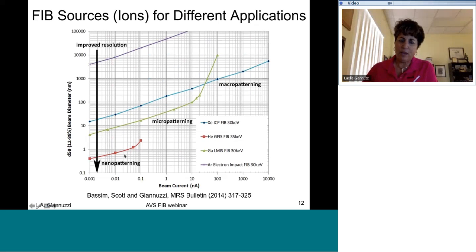Okay, on the very low end here, this is basically your gas field ionization sources. This is your helium neon sources. This graph here just shows helium. And what you see is that the currents available tend to be extremely low. The beam diameter tends to be extremely small, which also means the resolution is really sub-nanometer, and in some cases sub-angstrom. So these are going to be good for imaging as well as really good for nano-patterning. And then the ones in between, the one in green, this is your gallium liquid metal ion source, which most people are familiar with. And then the one above it is the plasma FIB, which typically we use xenon for most FIB applications, but you can use other reactive ions, for example, for SEM.